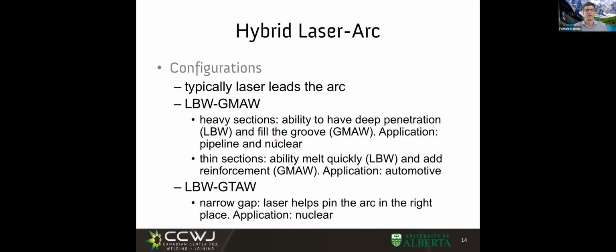Now, of the laser. When you're doing arc welding, you still have a problem of solidification, but you have a filler metal that has a special alloy such that when it solidifies, it's good. Now, in lasers, if you do it autogenously, it's going to be ugly. But even if you do a hybrid with MIG, what happens, and I know this for a fact because friends of mine were doing this in Germany, the filler metal stays close to the top, but the laser keeps drilling deep down. So you have good metallurgical properties where you had filler metal near the top, but deep in, where there was no mixture between the filler metal you added and the molten metal deep into the laser weld, that weld tends to be very brittle.